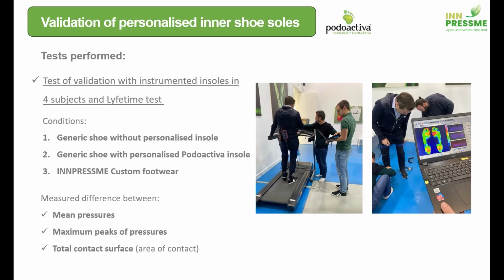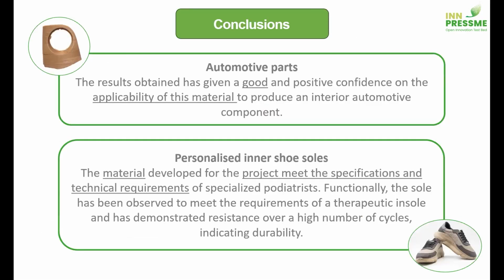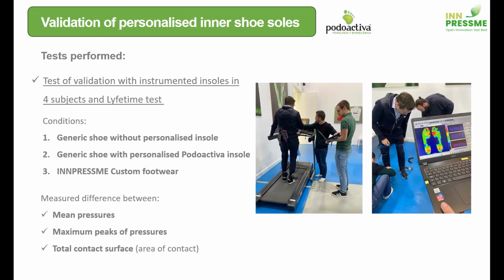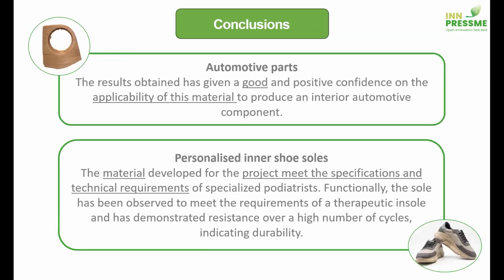But of course, we will need some more test cases, some more patients, to actually validate it. Another test they did, which is not shown in the picture here, is the lifetime test. They replicate the walking movement up to 10,000 cycles to see if the sole suffers any breakage or deformity, and the results were good. There was no change in the shoe.